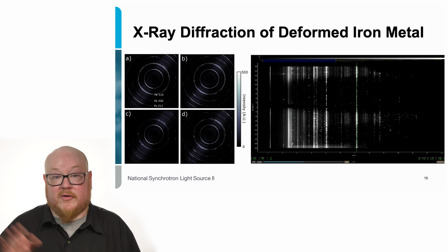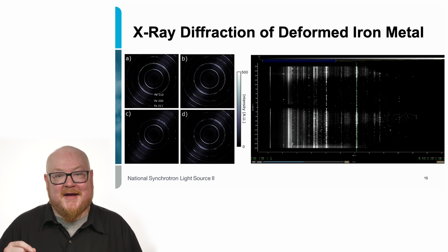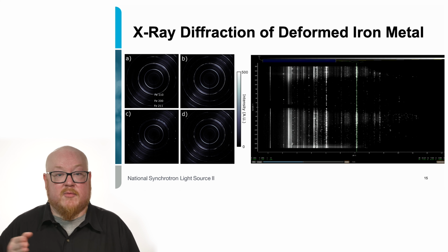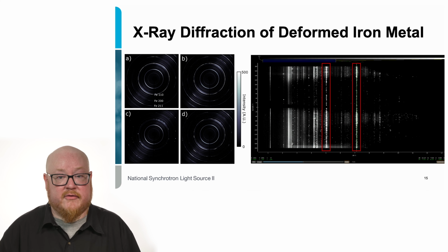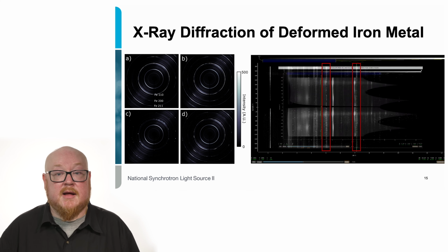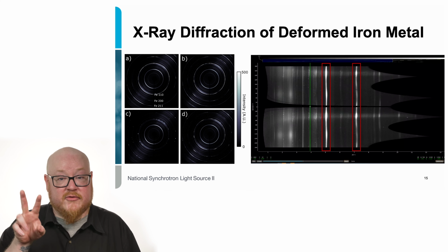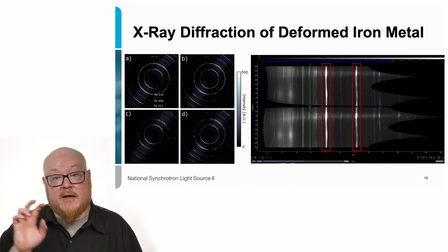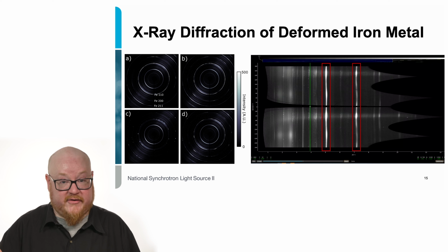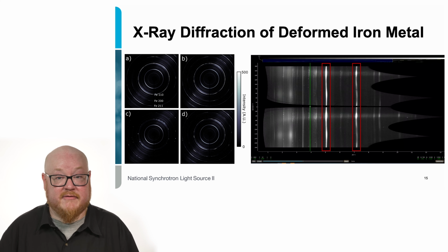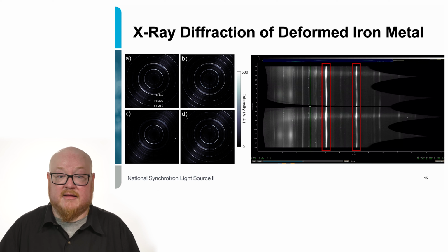So if we take those circles and we unfold them, doing a process that's called a cake plot, or slicing, that's the reason for the name of it. If we then look at a perfect circle on the cake plot, this will be represented by a perfectly straight line. In particular, I want you to look at these two lines right here, which are perfectly straight lines at high pressure before we do the deformation. Then once we do the deformation, you can see that those straight lines now wiggle back and forth. And those wiggles are representative of those ellipses that start to form when we have that deformation effect. So we are able to see exactly what is going on in these processes, and we're able to replicate what occurs during the forging process.